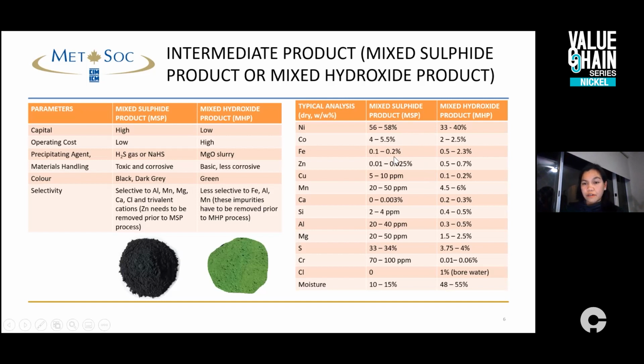And you can see in the iron, mixed sulfide is much more selective to the precipitation of iron, particularly if the iron is in the +3 species. With mixed hydroxide, it will precipitate very, very easily, but with mixed sulfide, it will first be reduced to divalent before it can be precipitated as iron sulfide. Also, look at manganese, which is, I think, the penalty element for downstream processing. With mixed sulfide, the manganese is at ppm levels, while in mixed hydroxide it could be up to 6%.